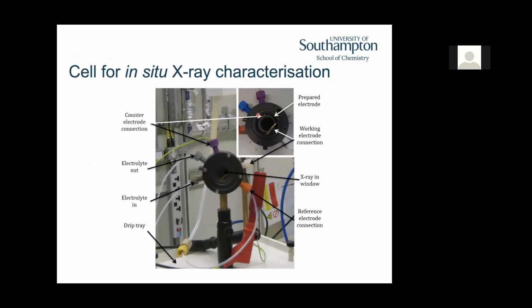So let's take a little bit more of a look inside the cell that my group normally uses. So we often use a carbon paper-based electrode, and we've painted the catalyst, for example, or our battery material ink onto this carbon paper. And that's the working electrode sitting here in the middle. We make contact to it with a gold wire, or another wire if we're going to look at gold. And then there's an X-ray transparent window sitting on top of this that's usually capped on.